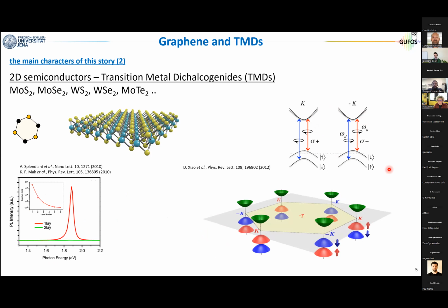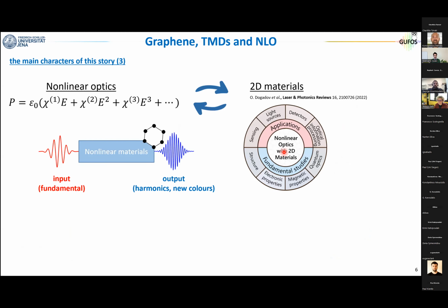Because in the K and K prime, the top of the conduction band has opposite spin. The top of the valence band also has opposite spin. This leads to the so-called spin valley lock. That means we can selectively excite one of the two valleys with light of opposite circular polarization. And this is the basis of a field that we call valleytronics. It means that we can use light to selectively generate, read and store information in the spin valley degree of freedom.